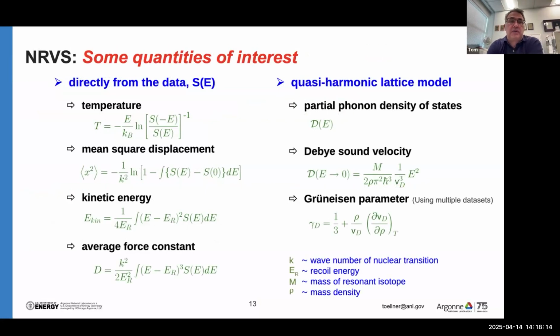Some other quantities, the column on the left are quantities you can get directly from the S of E. One is the temperature, just from the detailed balance, of course. Another is the mean square displacement. This is just gotten from the area under the curve minus the elastic line. And then, of course, as I mentioned, the kinetic energy can be gotten from the second moment of the S of E, and the average force constant.